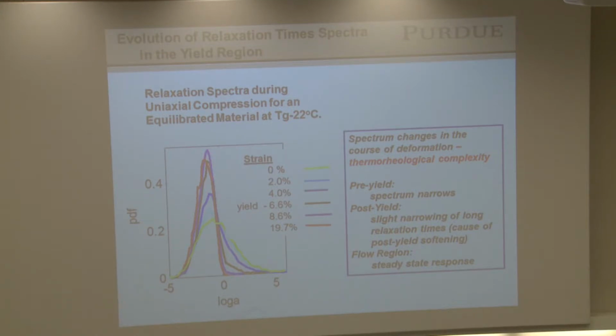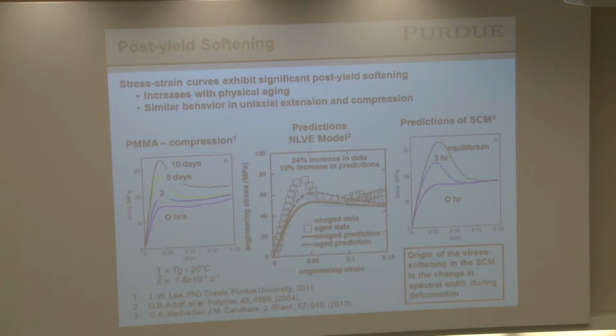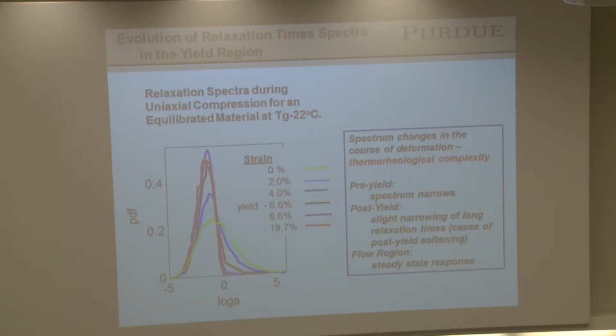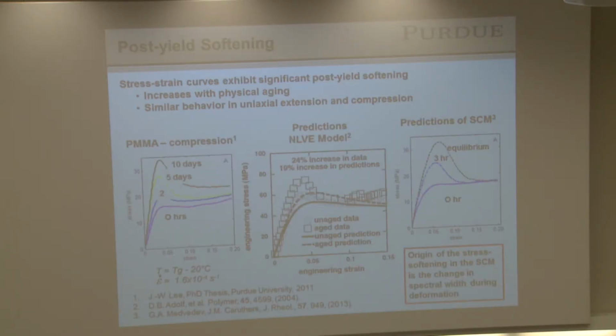More than that, I have a colleague at Wisconsin called Mark Ediger. He's one of the premier polymer spectroscopists in the world, perhaps the premier. He's actually now measured the width of that distribution during deformation, and aha, it narrows. So we have independent confirmation that this really unusual response, which comes out of putting these fluctuations into the system, has been confirmed experimentally.